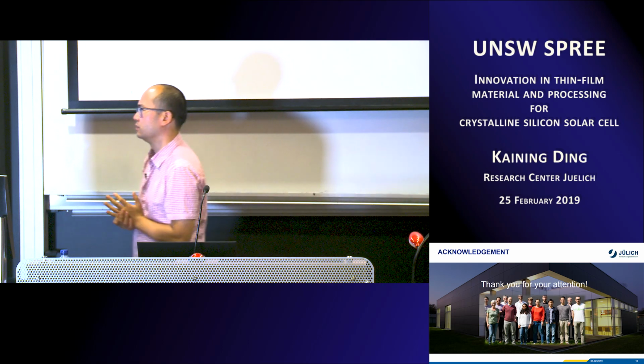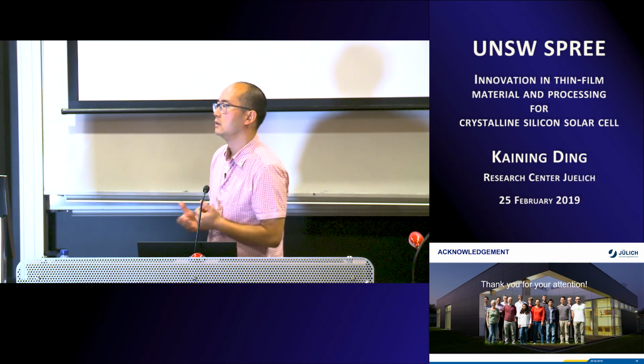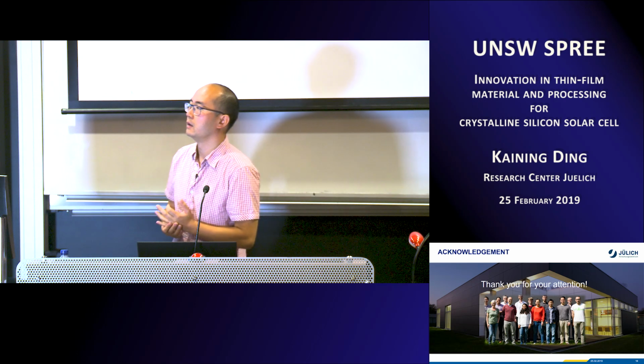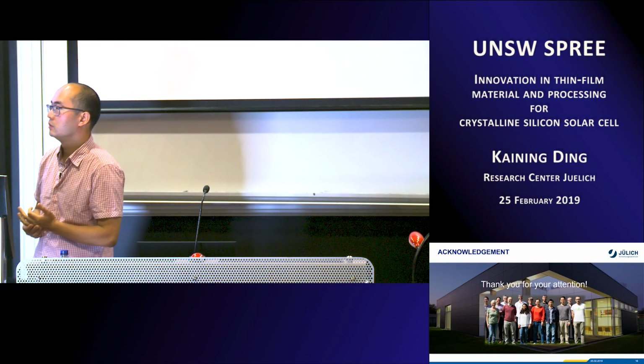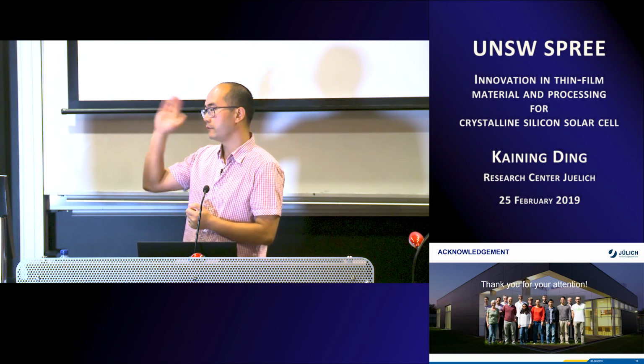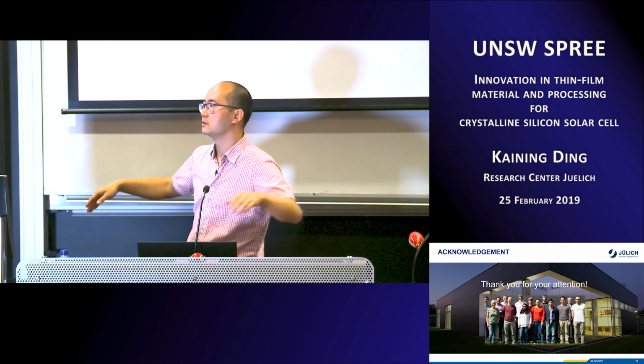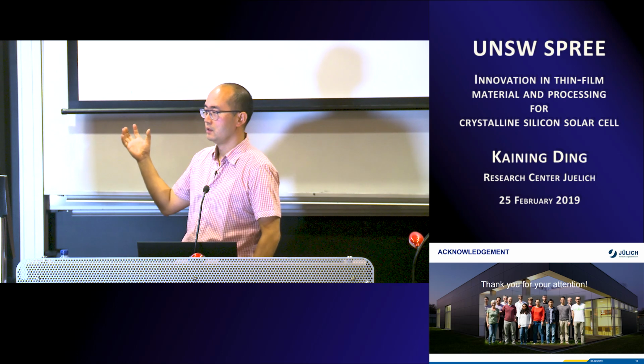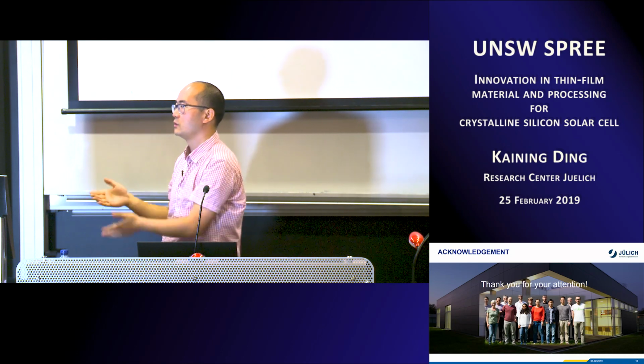In Europe, there is not a big discussion about hot wire CVD for PV, so I don't know why. But in China, there are a couple of companies having pilots in the volume of 100, 200 megawatt, using hot wire CVD to do intrinsic and doped amorphous silicon, and the results are actually quite good. But I think there are certain limitations in the throughput, because you have to deposit everything vertically. You cannot span meters of wires horizontally, so you let the wires hang, and therefore you have to deposit vertically. This means during mounting, you have to mount all the wafers, cover them with a mask or a holder and put it vertical, so it takes time.